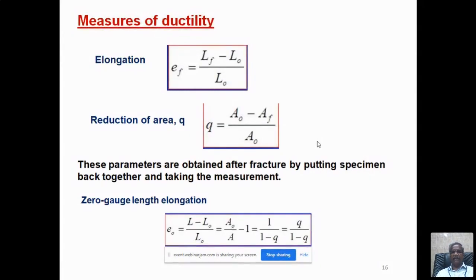LF is nothing but the final gauge length. Please understand it is the gauge length, the final gauge length. After fracture, you keep the specimen together and measure the gauge length. That is the final gauge length. Before testing, you measure the gauge length. You are fixing the gauge length, 50 mm or 100 mm or 70 mm, whatever, even 30 mm for a small specimen. That is the initial gauge length. And final gauge length minus initial gauge length divided by initial gauge length is the percentage of elongation.